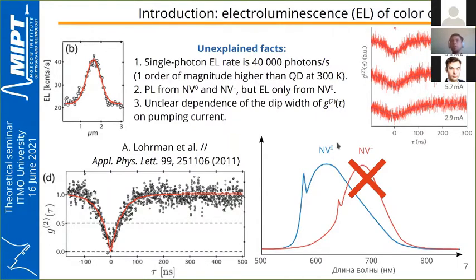Moreover, the NV center can exist in two different charge states, NV0 and NV-. During photoluminescence, that is optical pumping of the color center, researchers obtained spectra from both NV0 and NV-. Under electrical pumping, only NV0 was obtained. Moreover, an interesting effect was discovered: the characteristic time of the G2 function varied from 10 nanoseconds to microseconds under electrical pumping.